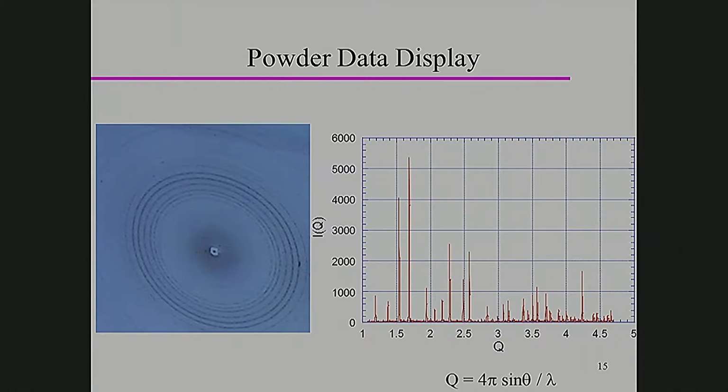The way we get these data is we basically mask our beam stop, okay? And if we know the sample to detector distance, we can integrate all of our data and just display it as one-dimensional data. So we eliminate any of those effects of some slight irregularities around those powder rings. But because we have such a limited amount of powder in a diamond cell, most of the high-pressure experiments will be done with a 2D detector.